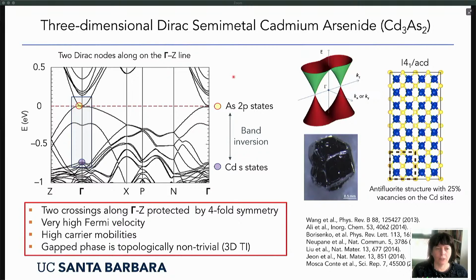So then more recently, starting in 2013 with this paper, it was predicted to be a three-dimensional Dirac semimetal. And here I show the results from electronic structure calculations. What you can see here is indeed, just like the cartoon picture that I showed you earlier, there's this band crossing here. And the good news about cadmium arsenide is that it's right at the Fermi level. This is also a relatively simple version, in the sense that we only have two of these Dirac nodes that line up along this fourfold rotational crystalline symmetry axis.